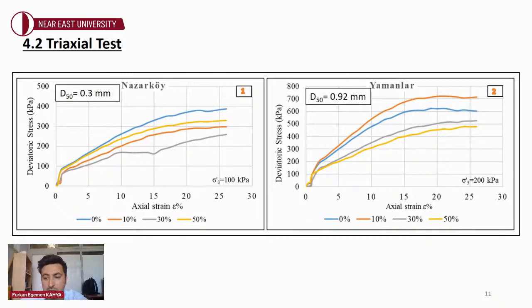On the other side, the shear strength of Yamanlar sand increases at 10% mica content, in contrast to Nazarköy sand. However, the shear strength of the Nazarköy samples decreases with increasing mica content. The maximum shear strength of these two sands was found at different mica contents. The reason for this is the median grain size difference of the two sands.